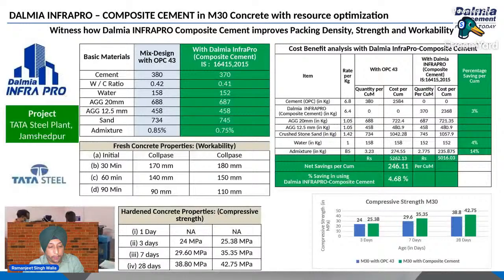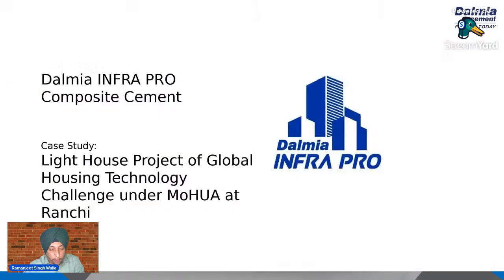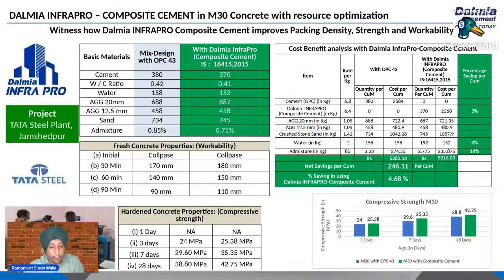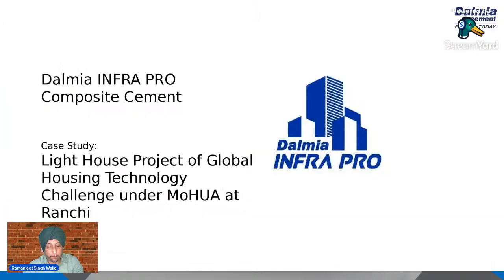This is Tata Steel Jamshedpur. We have done some trials of M30 grade where, with 370 kg of composite cement, we got M30 grade superior to OPC. The 28 day strength and also 7 day strength were higher than OPC, 42.75 MPa in 370 kg. The only thing is we just changed the chemical admixture.